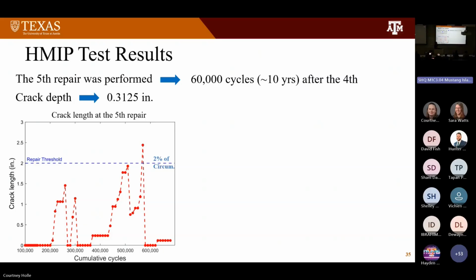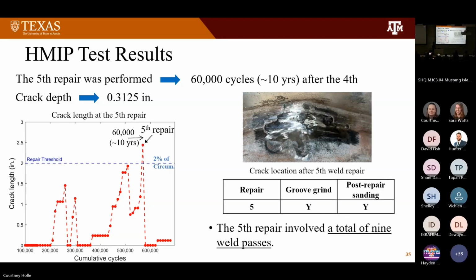So next, we decided to do the fifth repair. The fifth repair was done 60,000 cycles after the fourth, and this time the crack was really deep, with a depth of 5/16 inches. We used the same grinding and sanding method as the fourth. This time we applied a total of 9 weld passes: 1 fill pass at the bottom to fill the crack tip, two fill passes in the middle, and 2 more layers above them, each with 3 weld passes. This repair has been relatively effective so far.